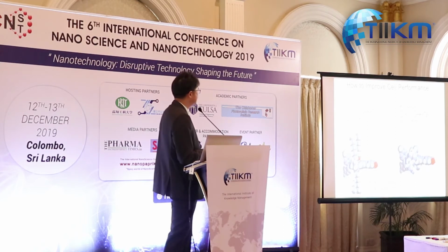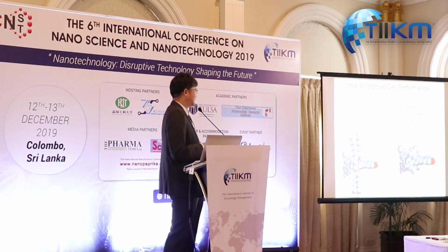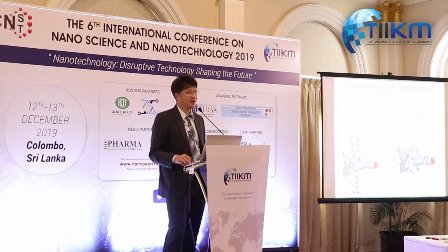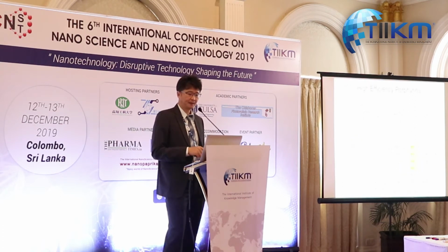In YD2-oC8, the long alkoxy chain at the ortho position of the meso-phenyl can reduce dye aggregation, and also the hydrophobic environment can block the approach of the electrolyte to the surface of titanium dioxide to reduce charge recombination, thus enhancing the VOC and PCE.